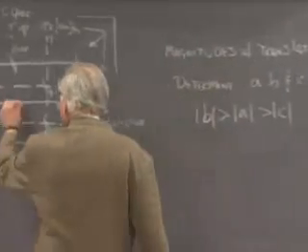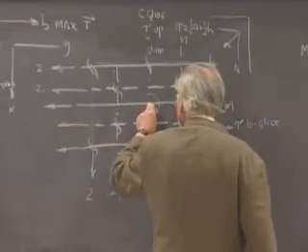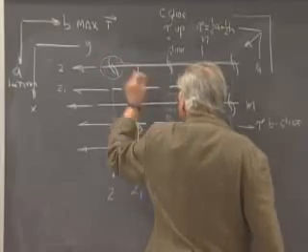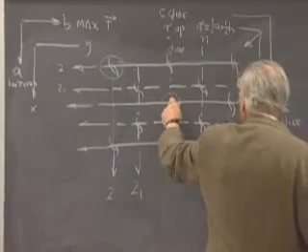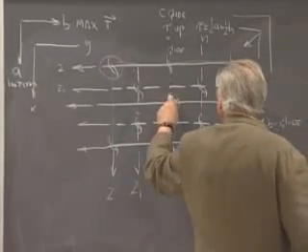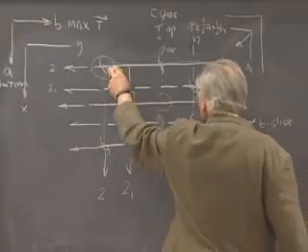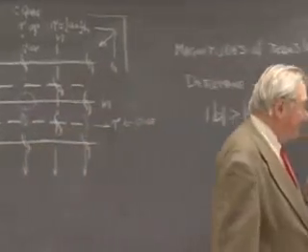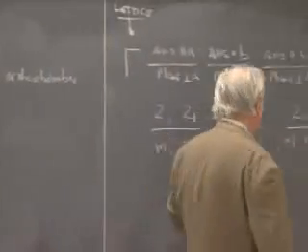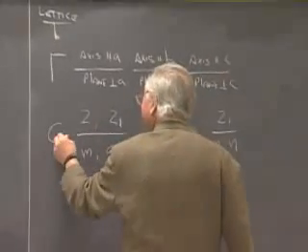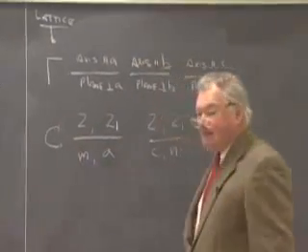We notice that the center of the cell at z equals 0 is the same as the grouping of atoms at the corner. So that is a side-centered lattice. The centered lattice point is the one coming out of the face which C emerges from. And so this is a C lattice.